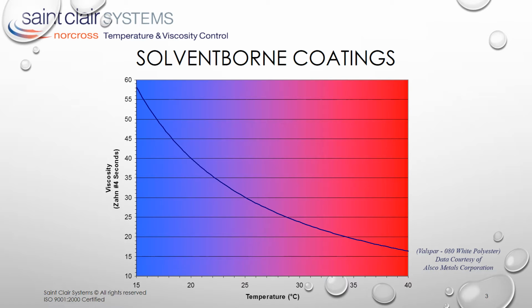Here we see the viscosity temperature curve for a common solvent-borne paint. It's the typical curve we're all familiar with. The nonlinear relationship, the viscosity falling as the temperature increases. Valspar recommends that this coating be applied at a viscosity of 26 seconds. If we extend this over to the curve and down, we can see that this correlates to a temperature of 28 degrees C.